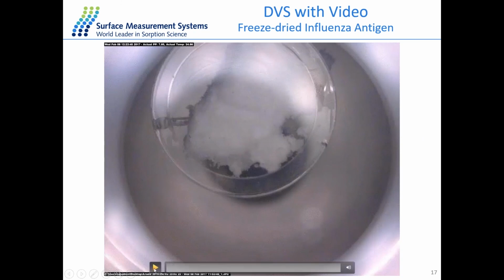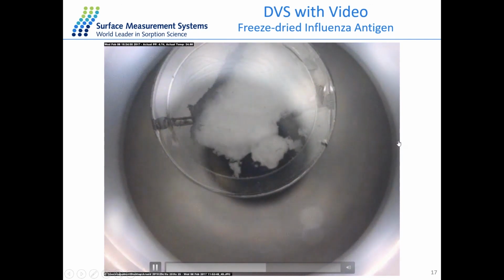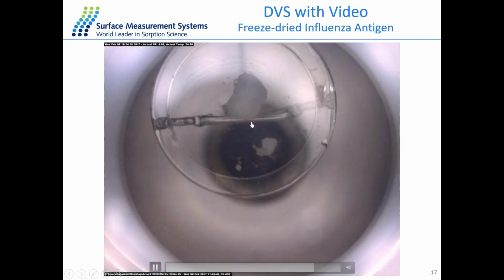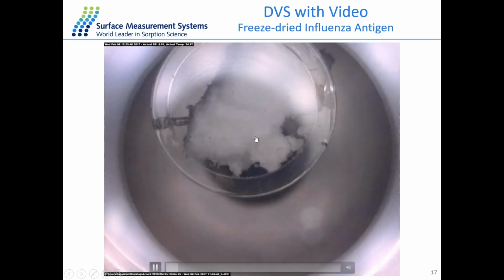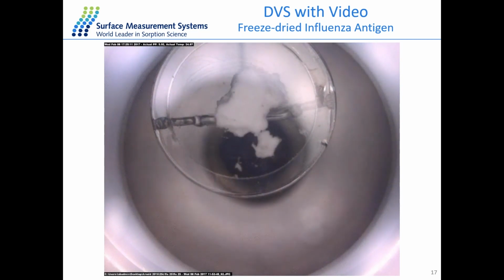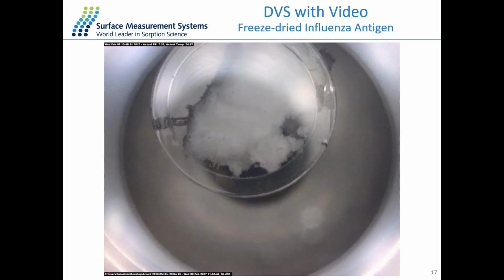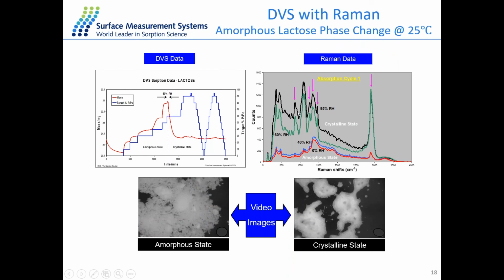So just for example, with a freeze-dried material like this one, we run the DVS experiment along with the camera, and at a certain point of humidity, the sample will just collapse, shrink, and then go to the liquid form. So the video camera is a very functional tool to compare any change in the color or change in different forms or the swelling or shrinkage behavior of the sample. And another combination with DVS and the Raman.